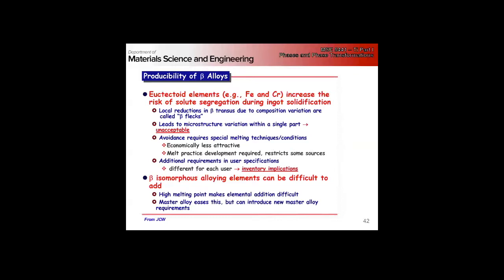So isomorphous alloying elements can be difficult to add, right? Because we've got a high melting point for things like vanadium and niobium, right? The same thing is sort of true for eutectoid when you have tungsten in there, right? So the way this is dealt with is what are called master alloys, right? The master alloys are high purity two or three component alloys that can be available, and they're semi-finished alloys, right? So they'll come from the melt as these master alloys, to which the processor will then make final alloying additions of things that are easier to put in, right?